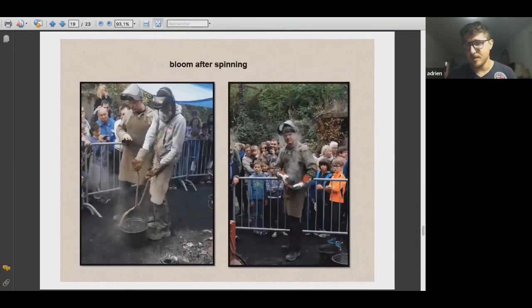So here there are 2 techniques. Some people forge it down directly, and others get it cold, cut it maybe before, or just when it's a very small bloom like this one, 3.5 kilos, you just get it cold. So a lot of slag is going to explode in the water, and the structure of the bloom is going to be really better to forge after. But you can strike a few times on it if you want to make a square or a rectangle before you cool it down. It's not going to be a problem.